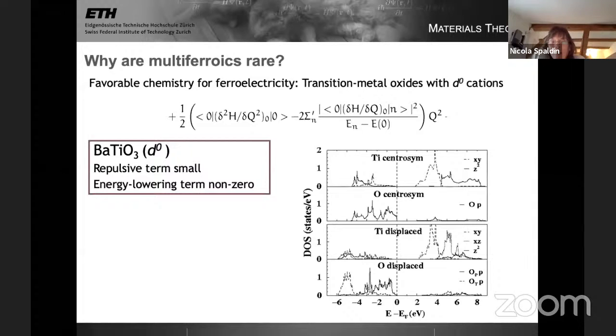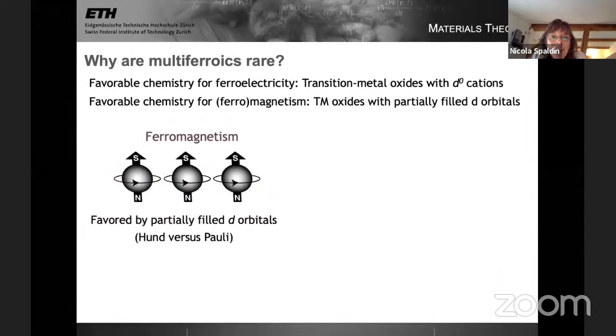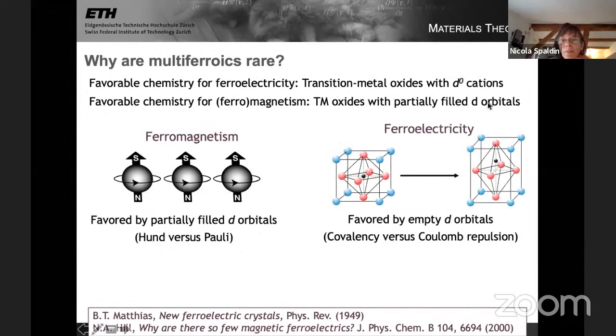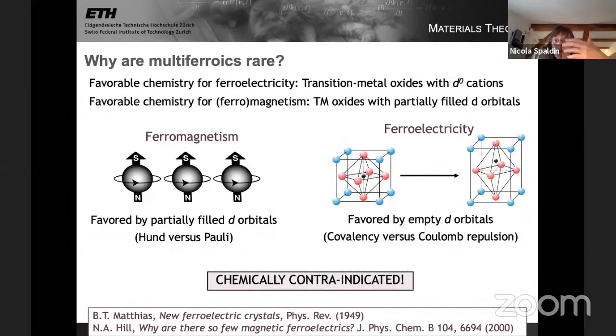Okay, so the message from that is that to be a good ferroelectric, we should have a d0 cation. Of course, you know that to be magnetic, we said at the start, if we want magnetism, then we want localized electrons in partially filled orbitals. And so to be a good magnet, my transition metal oxide should have partially filled d orbitals, which is then chemically contraindicated with the requirement for ferroelectricity.